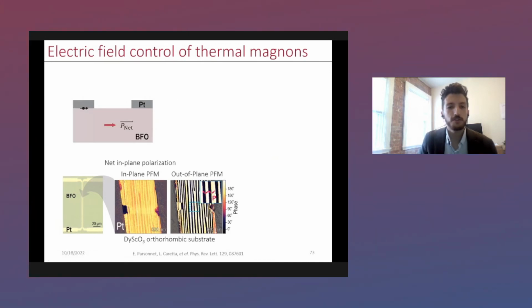And so the beauty of this net polarization is that we can latch onto it and use it to control magnetism of bismuth ferrite in the exact same geometry. By applying electric fields across these platinum electrodes, we can oscillate the polarization back and forth in this material with non-volatility, which also means we control the magnetism. We can do all this while doing this non-local measurement: we create magnons thermally and measure them electrically.